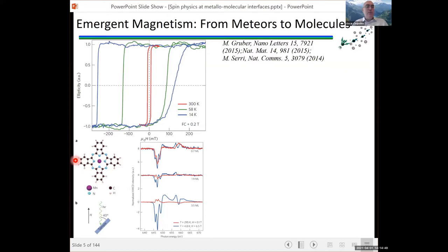And what they noticed is that when they had cobalt with these manganese phthalocyanines on top, and they field cooled their samples at low temperatures, they had this asymmetric hysteresis loop that they attributed to exchange bias. I slightly disagree, we'll discuss that later, but that's how it was presented first in Nature Materials.